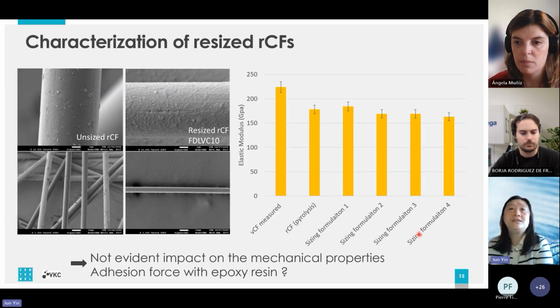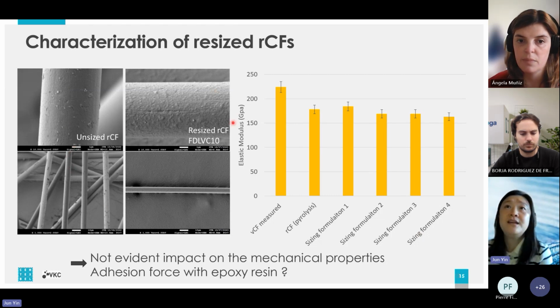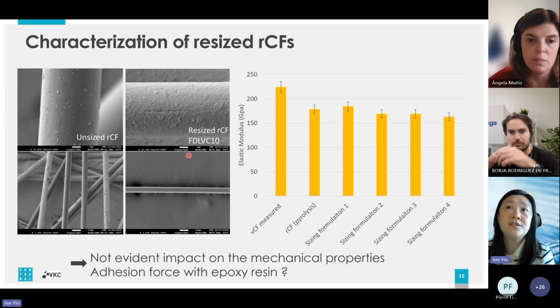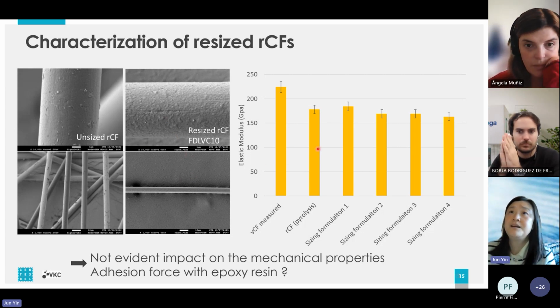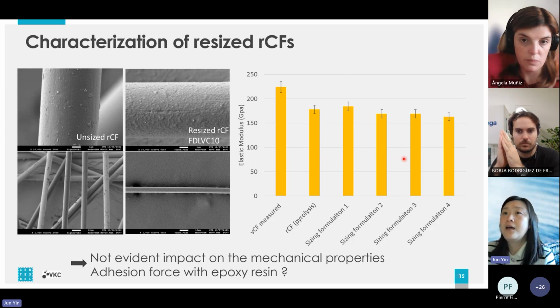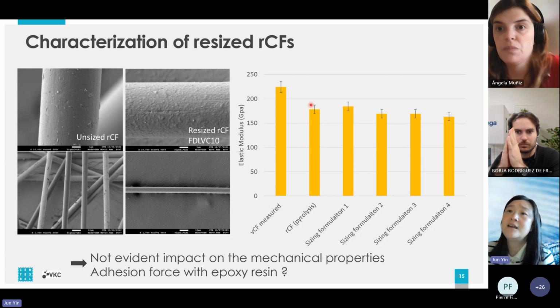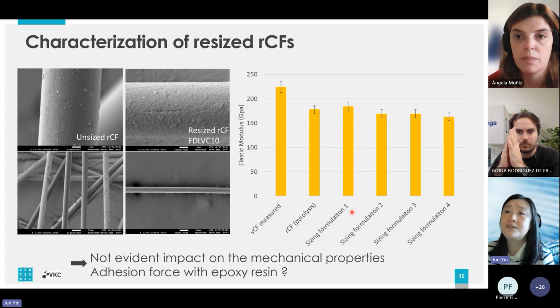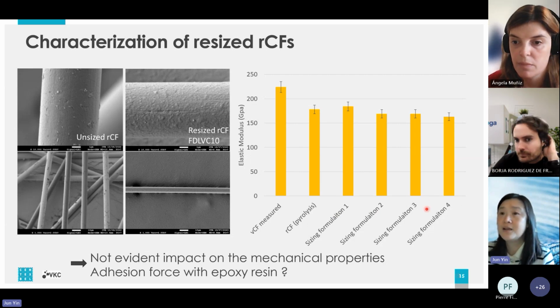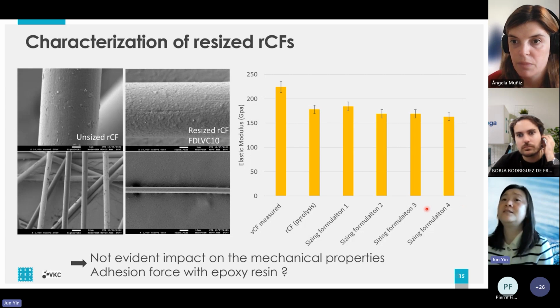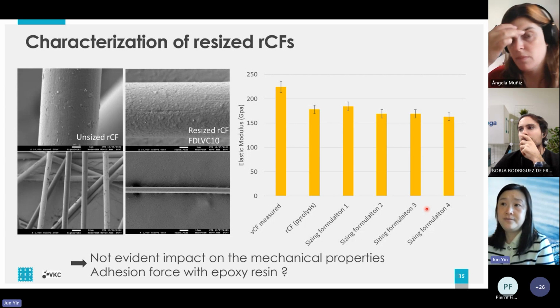So you can see some results. By SEM, we can compare the unsized carbon fiber and the resized carbon fiber. We can see the surface is more homogeneous than unsized fibers, and there's a small layer of the film former on the fiber surface. But when we compare the mechanical properties, the elastic modulus, the first column is the virgin fiber, the second is the recycled fiber that we compare with 4 different sizing formulations, but there's no evident effect on these mechanical properties. So I would say there's no big influence on the mechanical properties of the single fiber itself.